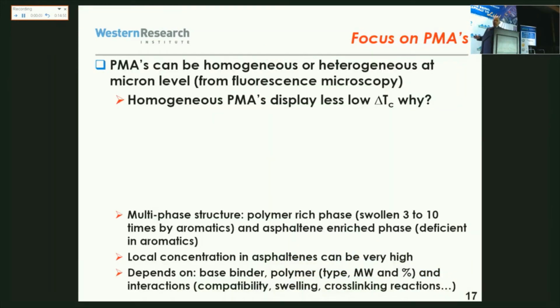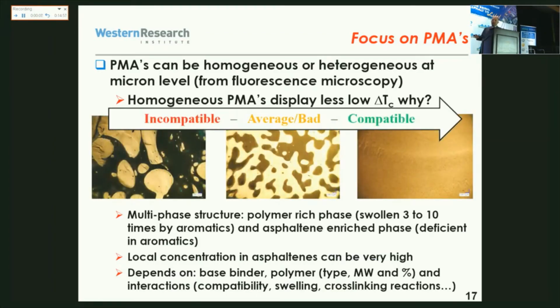So if we focus a little more on the PMAs, well, PMAs, as you all know, can be compatible or incompatible, and we can look at it under a microscope, and they are multi-phase structures. So basically, put the polymer in asphalt, it swells with the lighter molecules of the asphalt, and then the rest of the matrix is enriched in asphaltenes. So that's what this says. And this depends on the concentration of polymer, on the molecular structure of the polymer, and also on the composition of the asphalt base. So what we are trying to get is this level, this type of product.